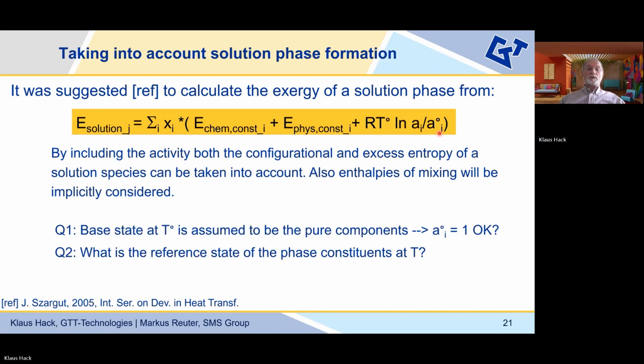But there is a problem. There is question number one: is it okay that the base state at T0 is assumed to be the pure components? In other words, all of these a_i0 values are equal to 1. Well, there are cases where this would certainly be okay, right? If you take the CaO MgO system at room temperature, there is a gigantic miscibility gap. You have pure CaO and pure MgO. You take the iron chromium system, gigantic miscibility gap in the body-centered cubic phase. You have essentially pure iron and pure chromium. But these are, let's say, the few cases where you can immediately say, yes, activity equals 1 is fine, but that is not general, right?